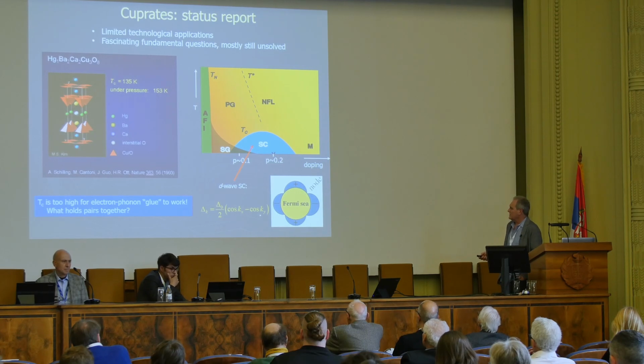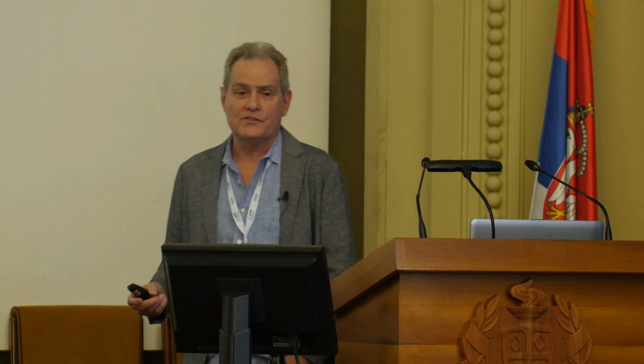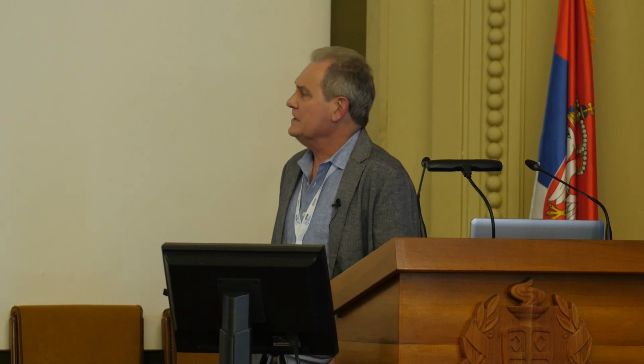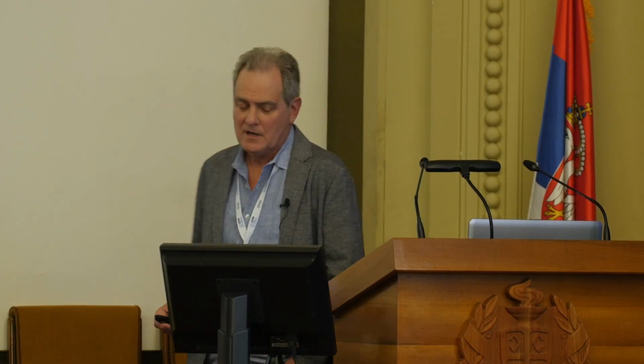But before, I'll say that there's one aspect of the system which we know pretty much for sure, and that is that the electrons do not form in S equals 0, L equals 0 pairs as in the original BCS theory. Rather, they form in D-wave pairs. And that means that there's quite a bit of interesting new physics coming from the fact that the D-wave order parameter goes to 0 along the 45-degree directions in the Brillouin zone.